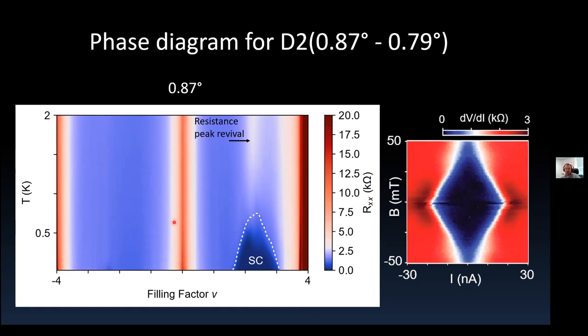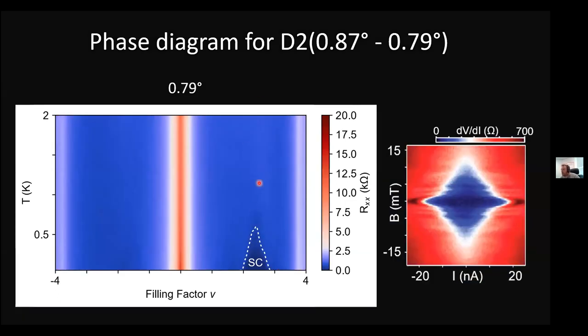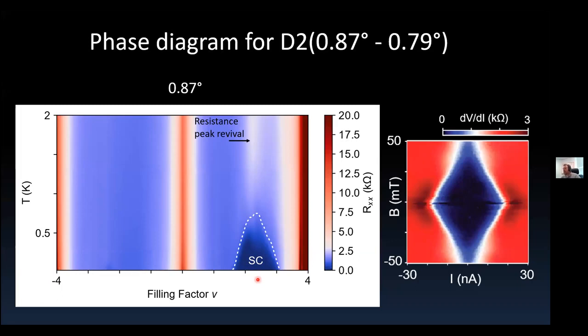I for sure don't have it in this presentation, so I can share it later. But I would say that there is still a kink in the RXY. The kink in the Hall resistance is a more sensitive probe than the peak in the RXX. We sometimes see in these color maps that there's not much change in RXX, but you can still see some small blip in the Hall resistance. So if you see a blip in the Hall resistance, there are probably some changes in RXY as well.